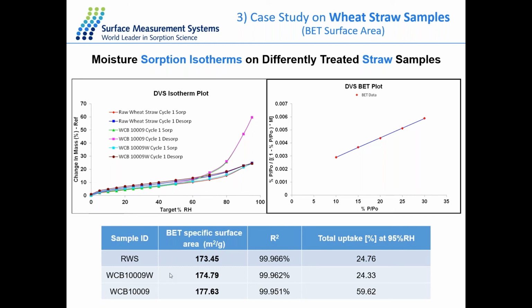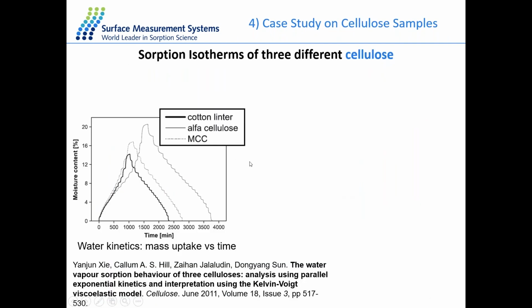And here it shows that after treatment, the BET surface area of the material slightly increased. And for the water capacity, it increased a lot. So this kind of treatment of the straw sample just increases lots of sites on the surface of the straw, and the washing also increases the amorphous content inside the material as well. And actually, the DVS technique can also measure the amorphous content of the material, and this could be a further research for this case study.